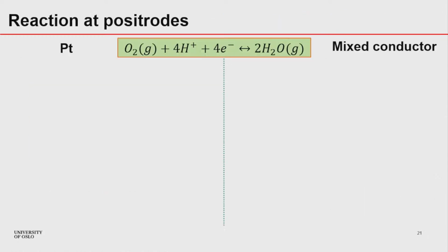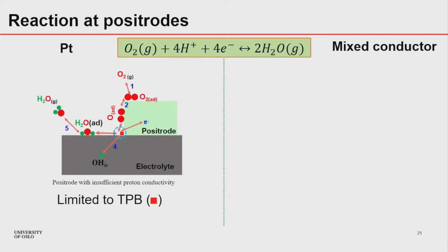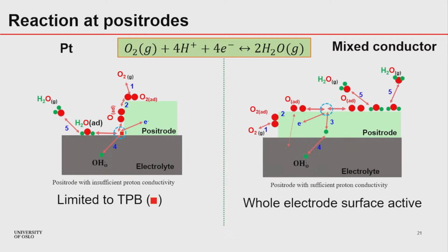Now, I will really rush through these slides because we have less time. But if we look at the reaction at positrodes, this is well known that if you have a platinum, for example, as a positrode, which does not have sufficient proton conductivity, the reaction will be limited to the triple phase boundary. And if you have positrode material with high proton conductivity, the whole electrode surface area will be active, and you will get a better performance in terms of electrochemical performances.